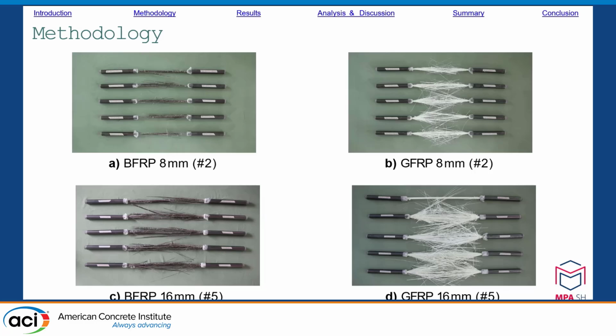The following photos show all samples of the test series with 0 freeze-thaw cycles on which tensile tests were carried out. It is noticeable that the fibers of the glass fiber rebars tear much more finely, whereas whole strands of fibers remain as bundles in the basalt fiber rebars. It also happened with the glass fiber rods with a diameter of 16 mm that they were pulled out of the anchor and the fibers did not fail.